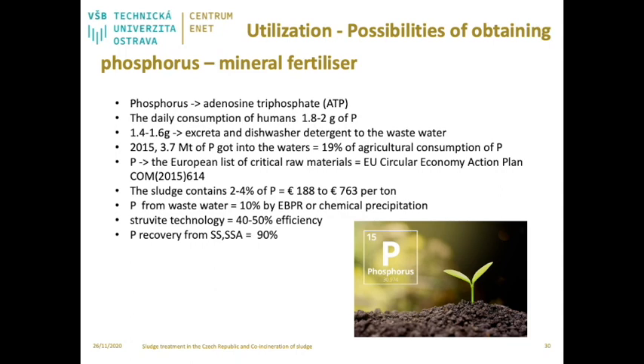Phosphorus is removed from wastewater by biological accumulation in biomass or by chemical precipitation. Approximately 10% of the total amount in the inflow thus flows from the wastewater treatment plant. The rest is bound by the activated sludge. Removal of phosphorus from the wastewater stream with struvite technology takes place at 80 wastewater treatment plants in Japan, USA, and Europe with an efficiency of 40 to 50%. Phosphorus recovery from sewage sludges or sewage sludge ash is much more efficient, reaching up to 90%.